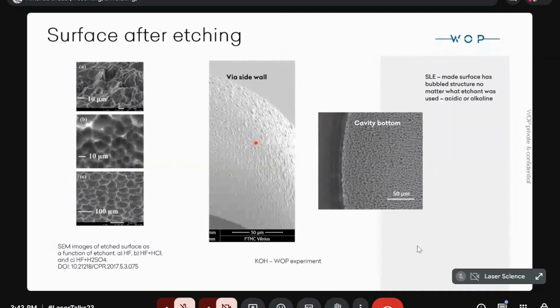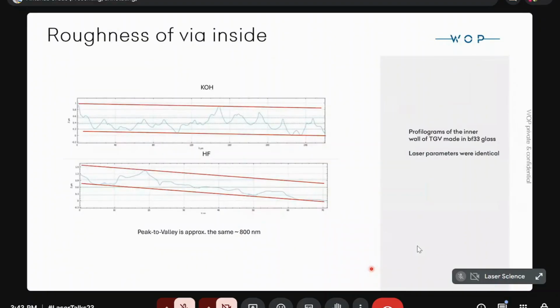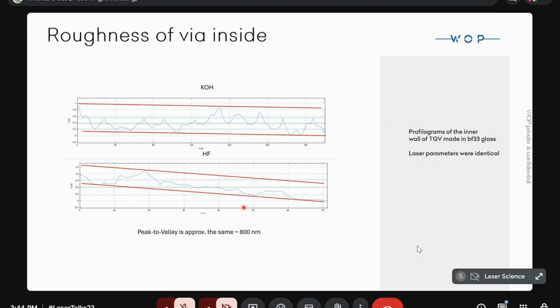Several microns on the surface, and let's see what it is in the depth. If we look at the side wall, you can see that the peak to valley is approximately the same, whether it is KOH or HF etching. It is roughly 800 nanometers. Not perfect, but quite good for the purposes the industry asks from us.